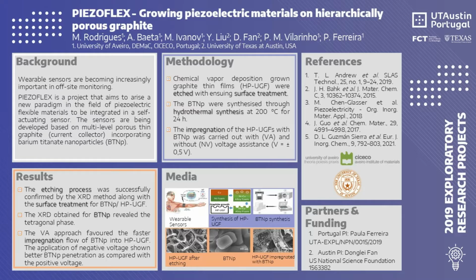The graphite templates are highly hydrophobic, and to be able to grow the barium titanate particles on its surface, the template's nature had to be counteracted. Thus, the template suffered a surface treatment to become more hydrophilic. The surface treatment consisted in submerging each template in nitric acid at 50 degrees Celsius for 2 hours.